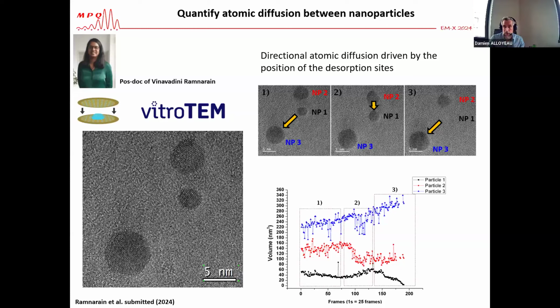So yes, the video is not running, but what you were supposed to see is the dissolution of these nanoparticles. Here you observe the evolution of the size of the nanoparticles as a function of time. And what we have been able to demonstrate is that nanoparticles are constantly exchanging matter during growth, and that there is a directional atomic diffusion that is driven by the position of the desorption site.